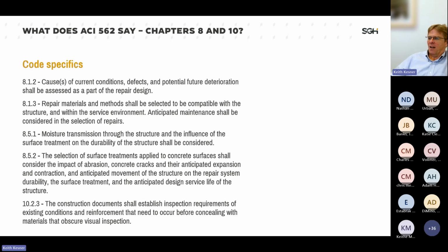So with some code specifics, thinking about causes of current conditions, making sure that our repair materials are compatible with the structure and the service environment, talking about considering moisture transmission through the slab. We're talking about adding an epoxy, which is a moisture barrier. So that needs to be considered. Interaction, impact of abrasion, cracking, and then establish construction inspection requirements so that we're actually getting what we want.